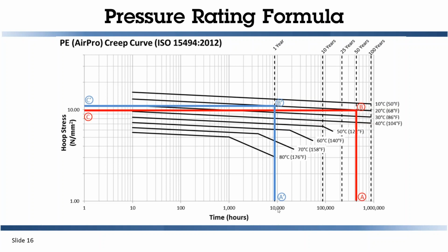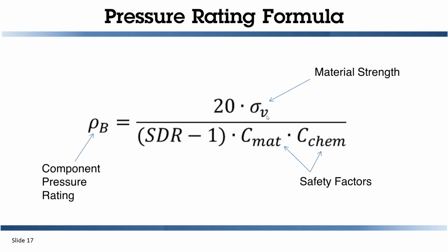If your system design is only for 1 year, you can go up this path, A prime, go to B prime, get that value from C prime. Those numbers get put into this formula, and obviously if you have a higher number, it's going to increase this value. So determining your lifetime is very important when selecting a material. We typically look at applications 25 years or above. Most of our applications are going to be for 50-year lifetimes.